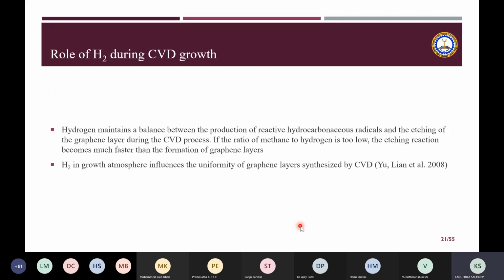What does hydrogen do? The hydrogen maintains a balance between the production of the reactive hydrocarbonaceous radicals and the etching of the graphene layer during the CVD process. If the ratio of methane to hydrogen is too low, that means the hydrogen is more, then the etching reaction becomes much faster than the formation of the graphene layers. So it is like a double-edged sword. You can't make it too more, you can't make it too less. So a very optimized hydrogen concentration, hydrogen flow, needs to be there to get the right amount of growth of graphene. So we can say that the hydrogen influences the uniformity of the graphene layers.